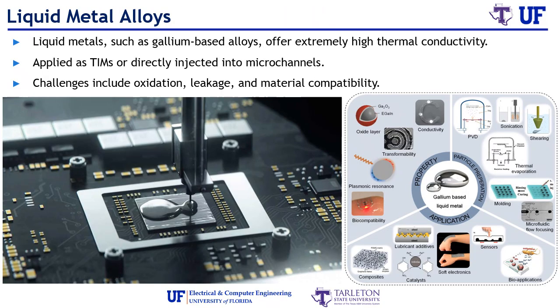Liquid metal alloys, gallium-based alloys mostly, can offer some of the highest thermal conductivity available, but it comes with its unique challenges. In the first image, we can see a liquid metal applied to a power module. This creates a low-resistance thermal path. In the second image, a microchannel cooling system utilizes liquid metal, demonstrating how it can navigate tight spaces while also maintaining rapid heat transfer. However, issues like oxidation and leakage must be managed carefully in a liquid metal system. For these reasons, they are known to require high maintenance and pose more challenges.